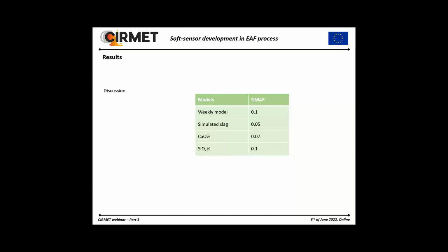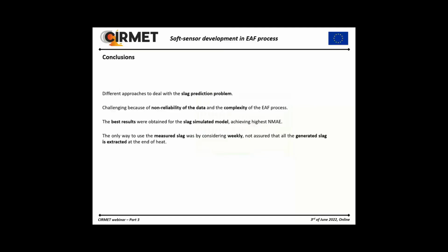And then we have to take into account that data-driven models with simulated data perform better than models fitted with real data. So that explains that the lowest error was obtained for the simulated slag model.